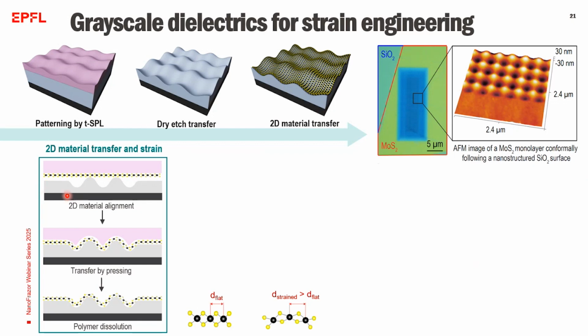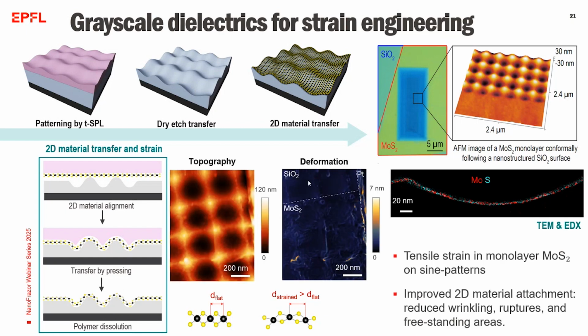And local strain in these 2D materials, which is MoS2 in this case, is achieved by pressing them against pre-structured substrates, and the material here is mechanically elongated during the pressing. After the attachment of 2D materials to the surface by van der Waals forces, the polymer is dissolved and the surface is clean, and consequently tensile strain in this patterned area is obtained. And as can be seen in this AFM and EDX characterization, the sinusoidal surfaces enable a conformal attachment of thin materials and mitigate issues like wrinkling, rupture, or freestanding regions. And in this way, we achieve a mechanically stable and improved dielectric-semiconductor interface.